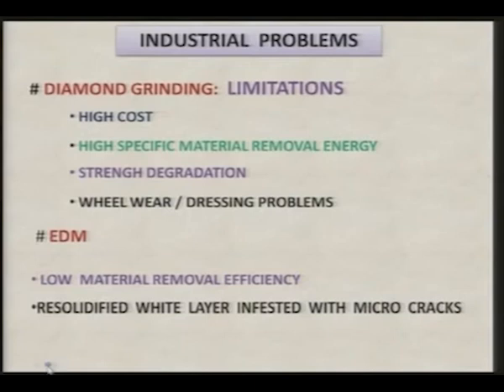After the EDM process, you get a resolidified layer, known as the white layer or recast layer, on the machine component, and this recast layer is very hard. It may be 2 to 3 times harder than the base material or the parent material of the workpiece, and it has micro cracks. So, after the EDM process, the component cannot be used as such in the sub assembly or assembly. It has to be treated such that this recast layer, resolidified layer or white layer is removed, and that requires additional time, one more operation, and it costs something to the component.